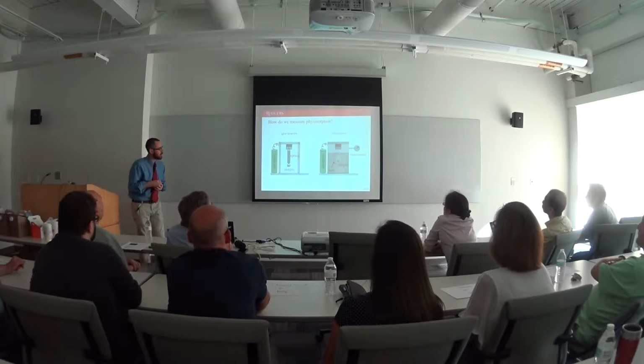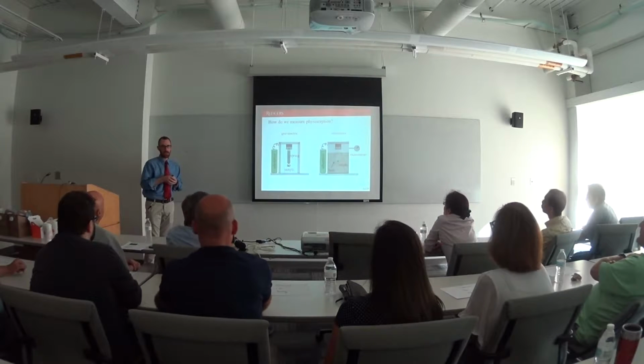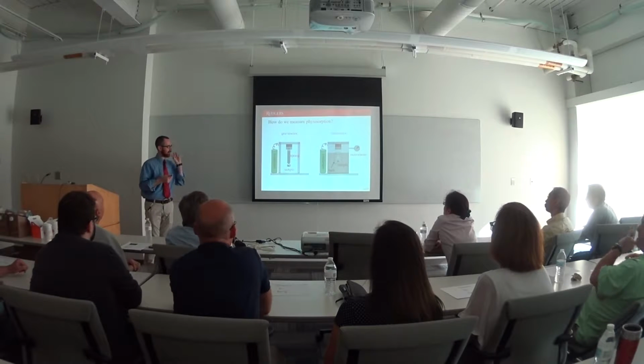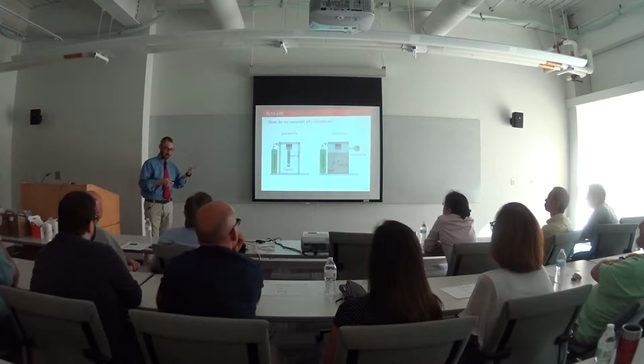The other method is called volumetric adsorption. In volumetric adsorption, we have the same cylinder, but instead of being attached to the whole box, it's attached to just a sample holder that's inside a temperature-controlled bath. And here we test the pressure inside the sample, repeatedly exposing the sample to little doses of the gas until the pressure doesn't change. And the pressure at which it doesn't change is the equilibrium. And that's the equilibrium uptake at one pressure.